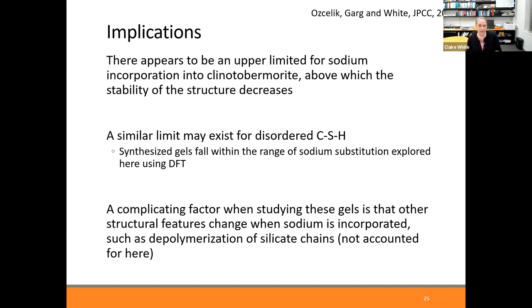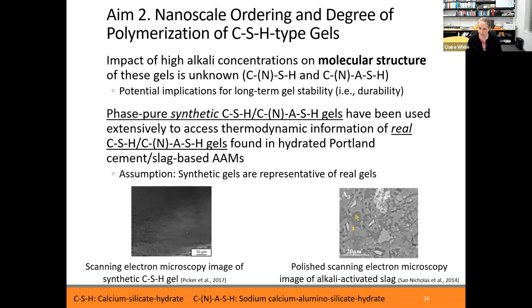So what I should mention is that there are a few caveats from the study that we've done, because there are other differences that we know occur in the structure of the gel when sodium is added to the system. What I showed previously was that the silicate chains in CSH gel, the conventional gel, are finite in length. When you add sodium into the system, it is known that these chain lengths get shorter. And so this will also impact the thermodynamics of the gel, which we haven't actually looked at with these computational calculations. But on the next slide, we're going to look at this from an experimental viewpoint.